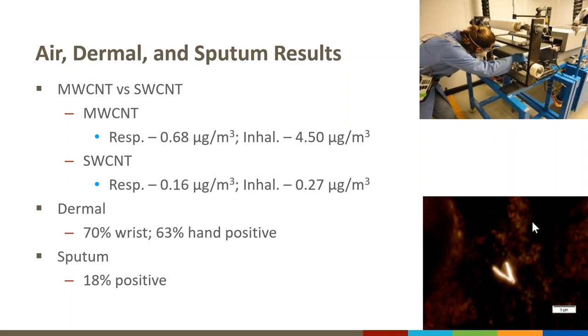So one thing that I wanted to get across to you, from the 12 facilities that we visited, I believe 10 of them predominantly use multi-wall carbon nanotubes as the carbon nanotube of choice. And there was a difference in exposures between multi-wall and single-wall carbon nanotubes. So multi-walls predominantly used in the composite industries in much higher quantities. So we actually saw slightly higher exposures with respirable coming in at 0.68 micrograms per cubic meter, inhalable about 4.5, compared to the single wall, which only had a respirable exposure of 0.16 and then inhalable of 0.27 micrograms per